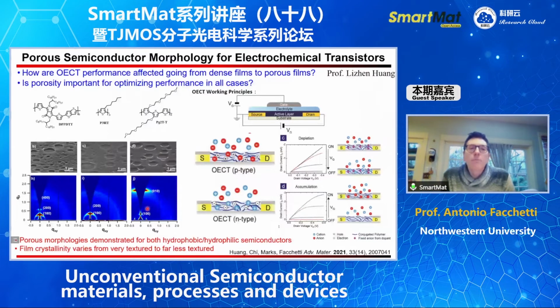Another thing we have done using porosity is to use it for electrochemical transistors. In terms of architecture, these devices are very similar to a top gate thin film transistor, but here you have an electrolyte. The way the device works is that by applying the gate bias, you have intercalation and redox chemistry in your semiconductor. So the semiconductor gets oxidized and reduced electrochemically. It's not only an electronic process. To achieve efficient redox chemistry, the ions of the electrolyte have to penetrate, so you have to have an efficient penetration of ions into your semiconductor.